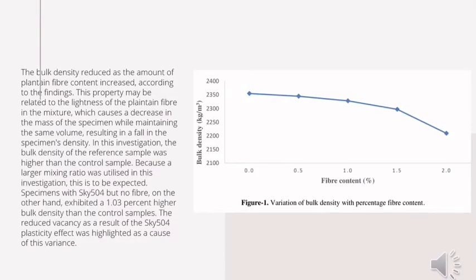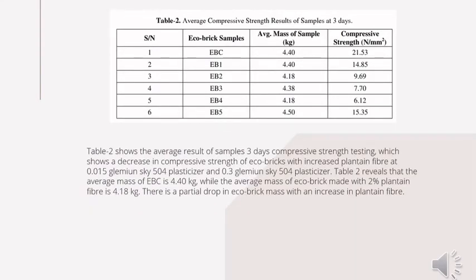Based on the graph beside, the bulk density reduced as the amount of plantain fiber content increased, according to the findings. This property may be related to the lightness of the plantain fiber in the mixture. In this investigation, the bulk density of the reference sample was higher than the control sample because a larger mixing ratio was utilized. The specimen with Sky 504 but no fiber, on the other hand, exhibited a 1.03% higher bulk density than the control sample. Table 2 shows a decrease in compressive strength of ecobrick with increased plantain fiber at 0.015 gram Sky 504 plasticizer and 0.3 gram Sky 504 plasticizer.